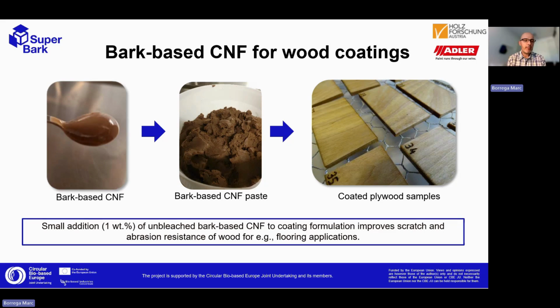So you start with the bark-based nanocellulose. Since nanocellulose contains a lot of water, the dry solids content of this nanocellulose is, if I remember correctly, something around 3%, 3-5%. It has a bit higher solids content than typical wood-based nanocellulose, but still contains a lot of water. You don't want to bring a lot of water into the coating formulation. So for that reason, we have been dehydrating this and making sort of a paste material, which is then used, as I said, as an additive in a solvent system to make these wood coatings.